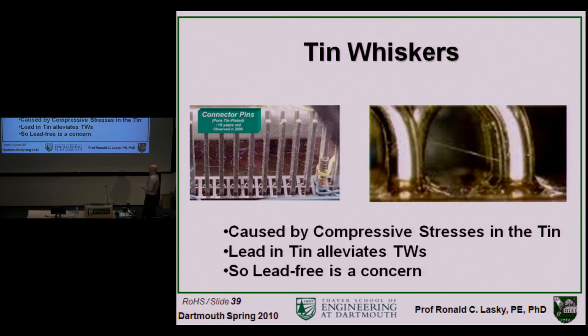It can be really pervasive. This is an example of outrageous amounts of tin whiskers. And people can produce it. This is the good news. Usually you can control something that you can make really bad and make it better. We can really produce tin whiskers like crazy. And here's an example where it's all over here. And we can make it go away. But the problem is we can't really make it go completely away. And that's what troubles people. So it's caused by compressive stress in the tin.